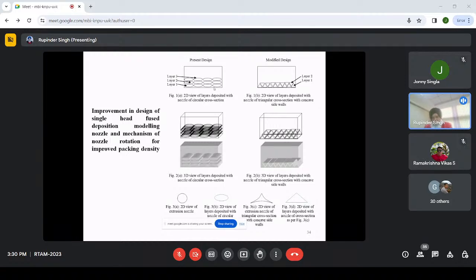Now, to overcome this problem, what we suggest is to use a nozzle like this. Now, this profile was cut on a brass nozzle using an EDM wire cut. But once we use the nozzle like this, we get an expanded shape, something like this. So these triangular layers were put over there. Then I have to make another layer. So through the stepper motor, the nozzle shape was changed, and the second layers were of the inverted triangles.